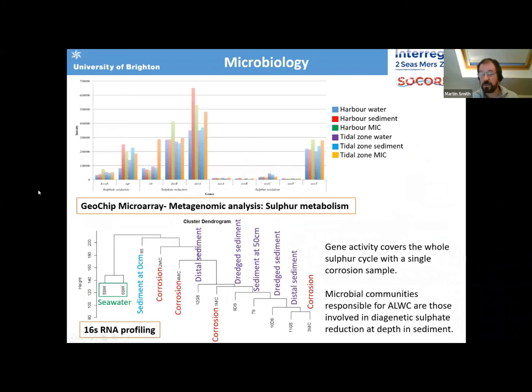So if we return to the microbiological analyses and we look at the sediment compared to the water column and the microbial samples, we're getting all the same sorts of gene activity, but when we look at the cluster analysis of the 16S RNA profiles, we can see the bacterial consortia in the corrosion are most similar to sediment 50 centimeters below the seabed. And the seawater samples are most similar to sediment at the surface.